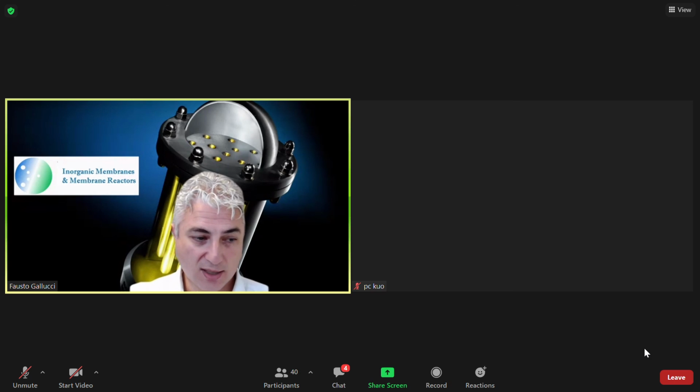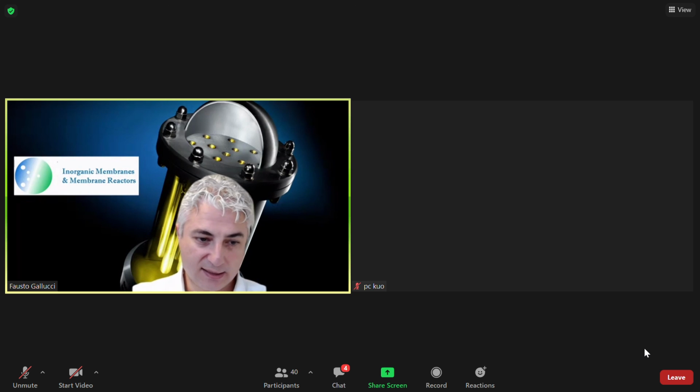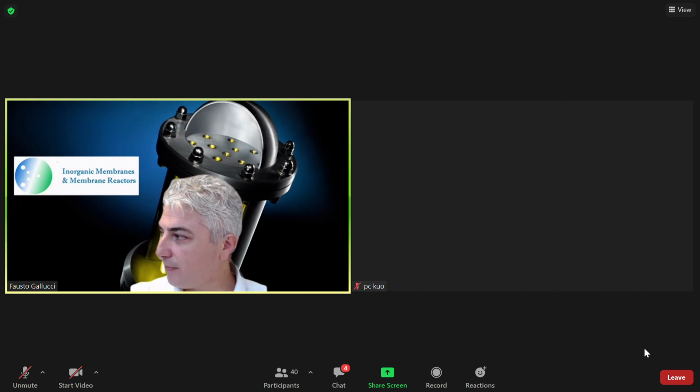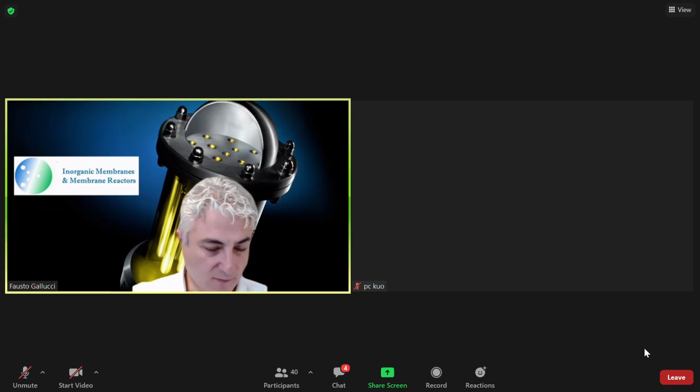Ethanol, the same, because ethanol becomes methane at high temperature, then you have the same problem of reforming of methane. So I think temperature is the main problem. Of course, we are also working on different materials, but unless you put electricity in, which is one of the research lines that we are doing, but if we do only pressure-wise, the palladium membrane is still the one that is more efficient for this separation, for the hydrogen.